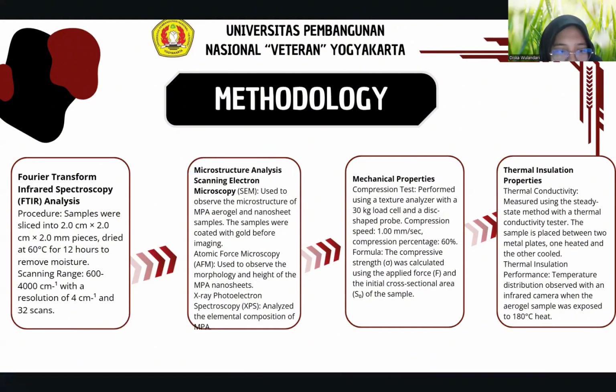Next is microstructure analysis. Scanning electron microscopy, or SEM, is used to observe the microstructure of aerogel samples and MPA nanosheet. Samples were coated with gold before imaging. Atomic force microscopy, or AFM, is used for observing the morphology and height of MPA nanosheet. X-ray photoelectron spectroscopy, or XPS, analyzes the elemental composition of MPA.